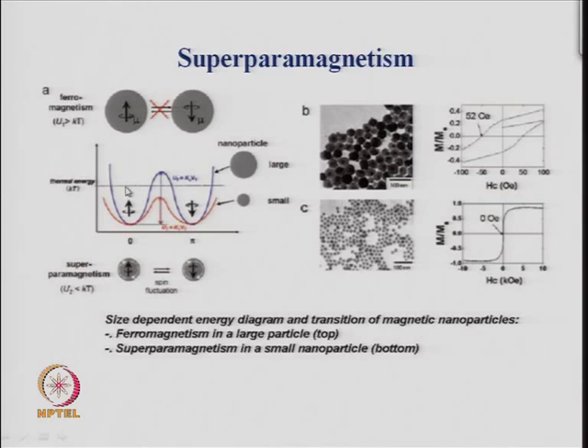So, now, if at room temperature the thermal energy has a value of this nature, which is less than the value required by the large particle, but this energy is sufficiently more than the energy required to change the magnetic vector in a small particle, then you will automatically have this change in the spins. So, you can do this spin flipping at normal temperature, and you will have both possibilities in your system. And so, this spin fluctuation then leads to superparamagnetism.